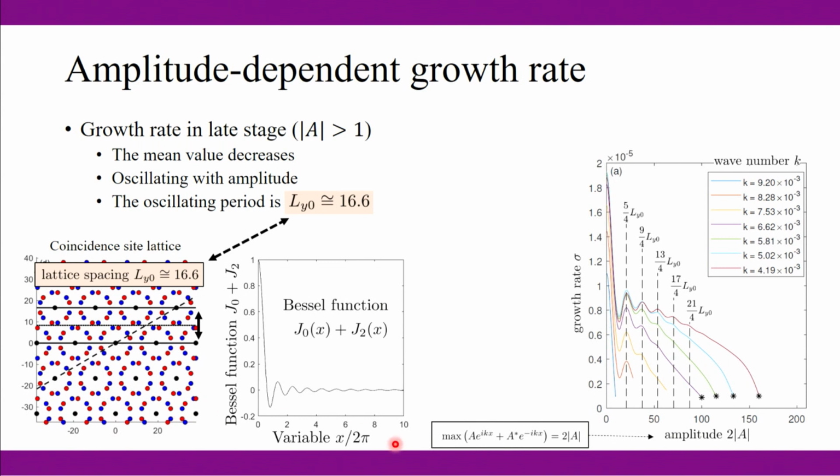So when we measure the growth rate as the amplitude is amplified, we are no longer talking about the linear regime. We're talking about the amplitude now, right? Its magnitude is larger than 1. Before, to really study the perturbation, the amplitude had to be small, or at least Ak had to be small, as we introduced yesterday. But now let's say the amplitude, Ak, is no longer a much smaller number, so you can see a rather pronounced amplitude. Along the wave, you measure the growth rate versus its amplitude.